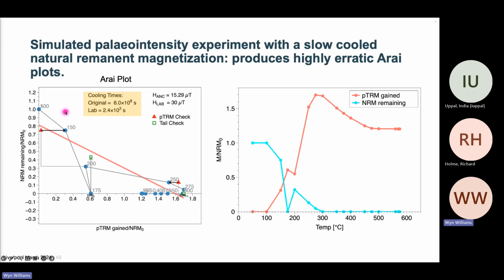And we get something that's not a very nice Arai plot. All right, we get these crazy variations. However, there are indications, I think, that some things are not right. So these are our PTRM checks. If it was correct, this curve would point to 150. So it's basically remagnetizing it to 150, and it's not where it should be. We've got another one here at 250, which is not so bad.